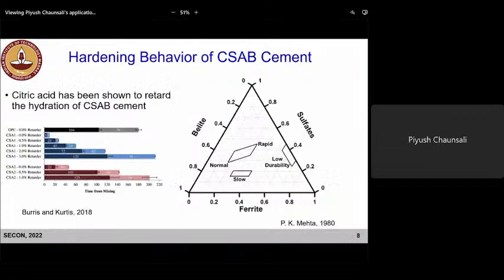So we know about the phase composition. Let's say now what happens to the hardening behavior, how quickly these CSAB cement harden, right? So that's also very important. So first let's look at this again, the ternary phase diagram. So you have basically belite is increasing in this direction you can see. So depending on the amount of these phases, silicates, sulfates, ferrite, the hardening behavior of CSAB cement will be different.